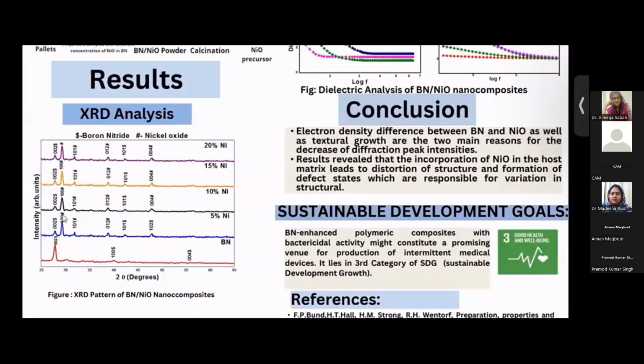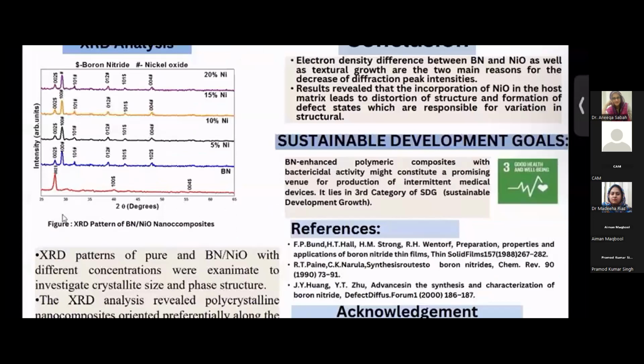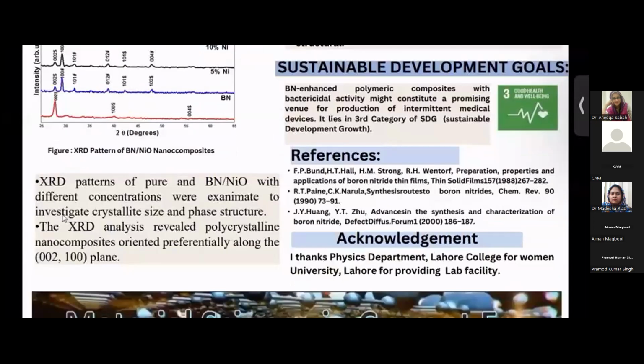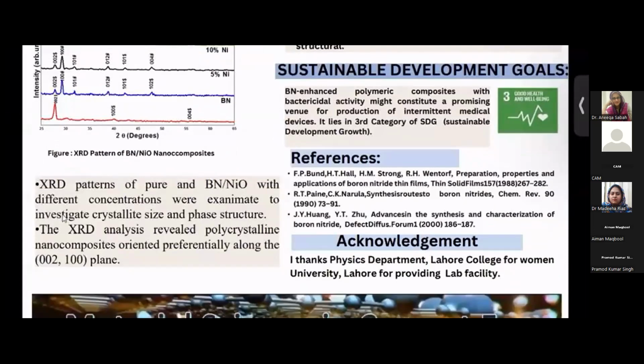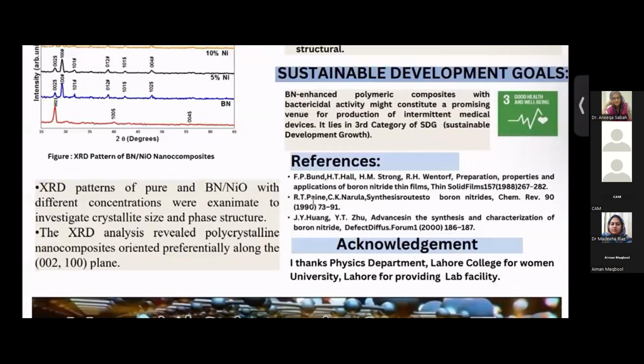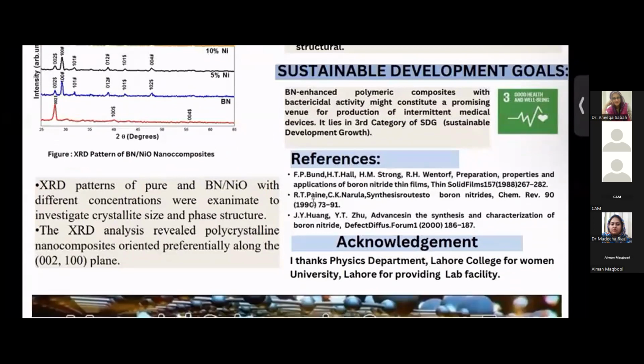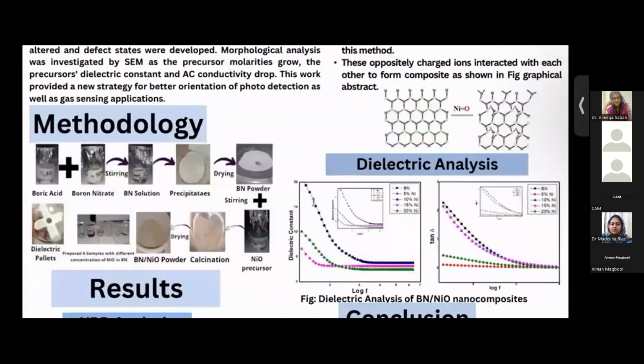XRD patterns of pure boron nitride and boron nitride nickel oxide with different concentrations were examined to investigate the crystallite size. XRD analysis revealed polycrystalline nanocomposites oriented along the 002 and 100 planes. Dielectric analysis. As you can see from the graph, the dielectric constant of boron nitride is very high.